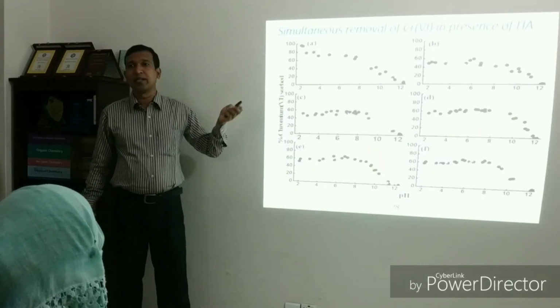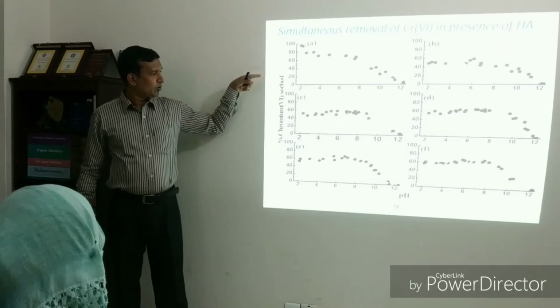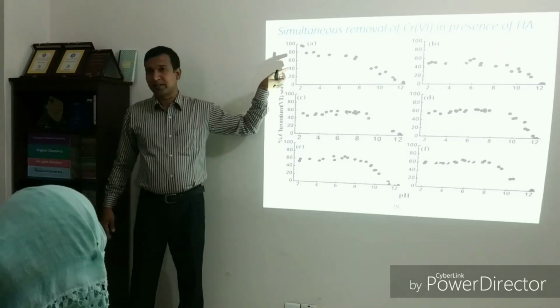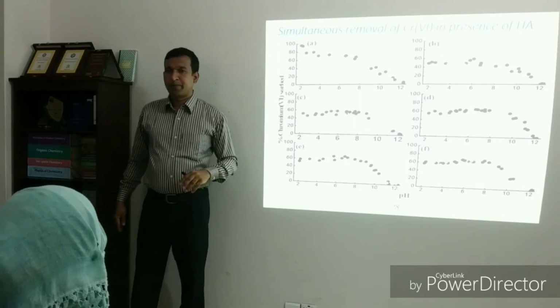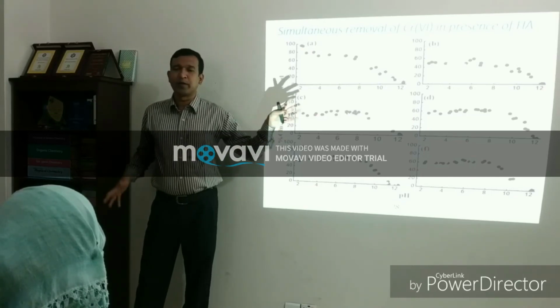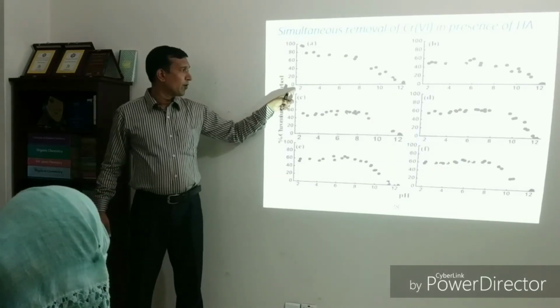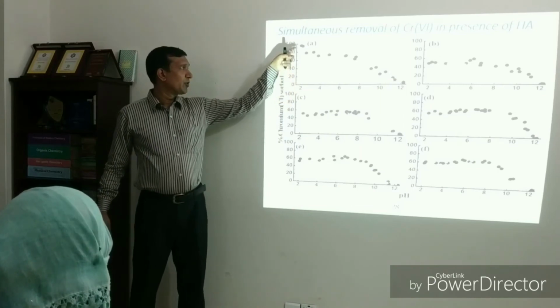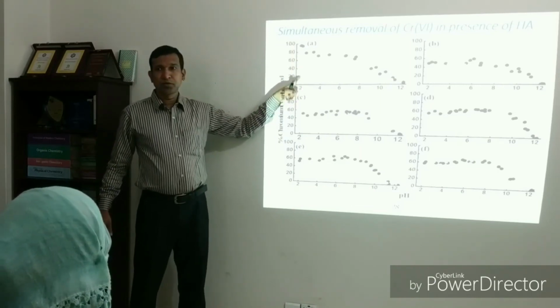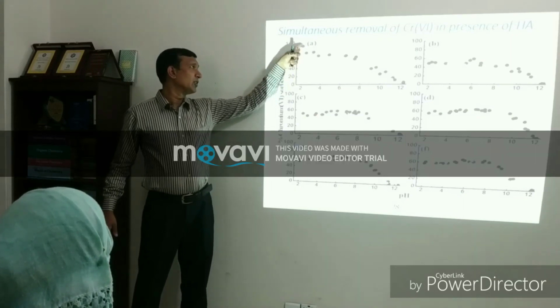Could you mention the pH effect on the adsorption? Yes, that is the adsorption edge. The adsorption edge is the study of the effect of pH on adsorption, in which pH the adsorption is favored. Yes, it depends on the surface. For example, in case of birnessite, it's a very interesting question, the maximum adsorption occurred at pH 2. So in case of birnessite, pH 2 is the optimum pH for chromium adsorption.